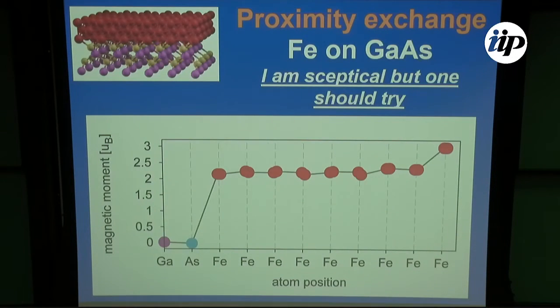Can you imagine that you have an induced spin just in equilibrium, iron and gallium arsenide, and you go to 200 nanometers? Well, first of all, there are materials. You can do the Kerr effect, and people do that routinely because we do spin injection. Only in spin injection, which is a kinetic, non-equilibrium effect, you have this injection going to maybe 200 nanometers. And it just decays very quickly. Sure, it's a very different effect. I'm essentially done, sorry, because this is a discussion already.